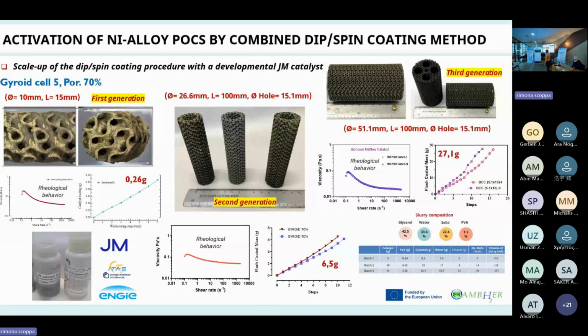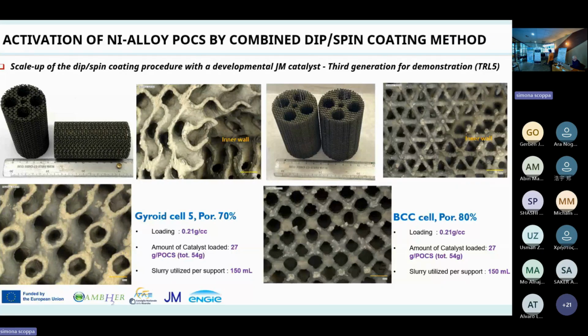What we did was start from little pieces, and we were lucky in this case. We used the JM catalyst, the developmental catalyst for the project. We were lucky during the scale up because the rheology did not change so much when we increased the amount of powder for the activation of bigger pieces. This is the ideal situation. So we used the same composition of slurry from the little pieces to the bigger pieces. And these are the structured catalysts we obtained at the end.